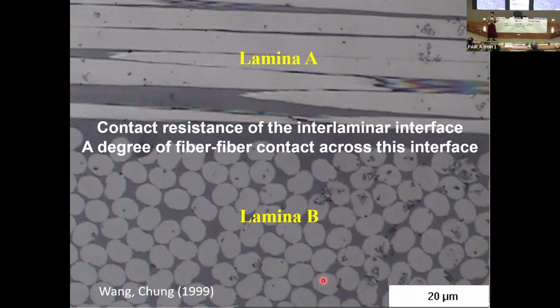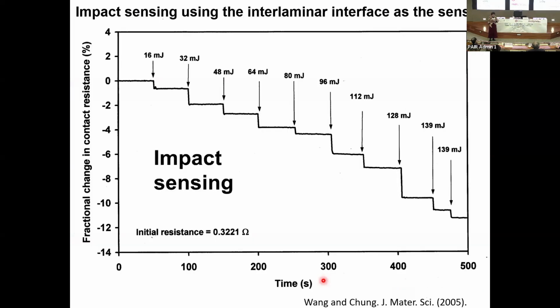And I developed an electrical method to zoom in electrically at this interface by measuring the contact electrical resistance. And it turns out that there's always a degree of fiber-fiber contact across this interface. And so the resistance is never infinity, and it's very sensitive to delamination and other factors. This is an example of that.